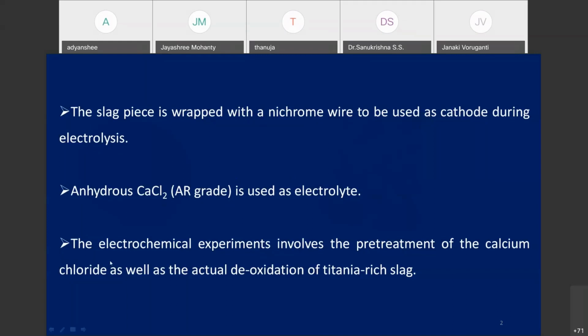Another thing is that this fused salt cell electrolysis involves pre-treatment of calcium chloride as well as actual deoxidation of titanium slag. So in such electrolysis, first you have to carry out pre-treatment of your molten salt, because pre-treatment is highly essential to remove any moisture or any other substances that will hamper the electrolysis process. That part will be removed during the pre-electrolysis process. Otherwise, it purifies the electrolyte.